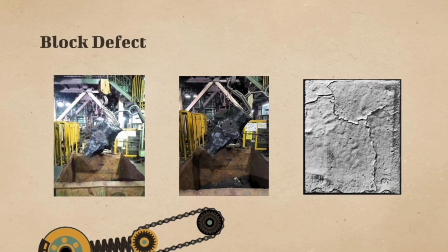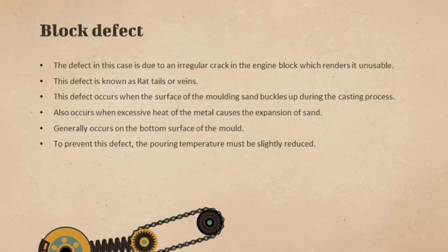Secondly, we have the block defect, and in this case, the defect is an irregular crack in the engine block, which makes it unusable. This defect is known as rat tails or veins. This defect occurs when the surface of the molding sand buckles up during the casting process. This defect can also occur when excessive heat of the metal causes the expansion of sand. It generally happens on the bottom surface of the mold. In order to prevent this defect, the pouring temperature must be slightly reduced.